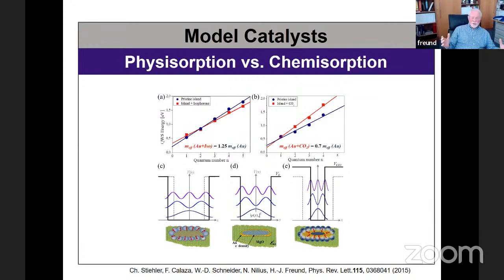Well, the particle describes sort of a pot of electrons, right? And you put the electronic states into this pot. You will have the various electronic states here, in the simplest case a particle in a box. If you shrink the pot, then the states will have stronger energy differences, right? And so that's one of the reasons why this happens, because when the molecules are at the rim, they sort of take electrons away from the cluster, and that means that the electrons have to sit in a smaller potential well. And that gives rise to these different slopes that you see here.